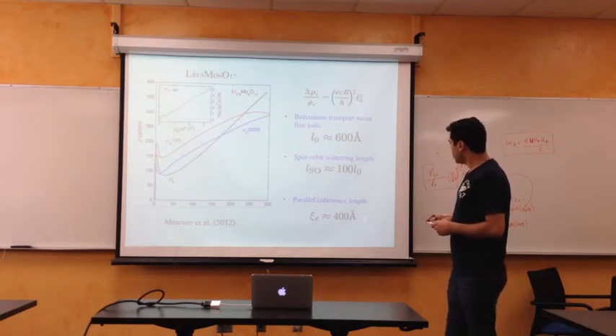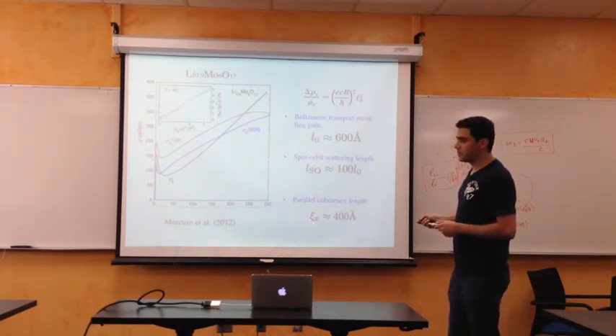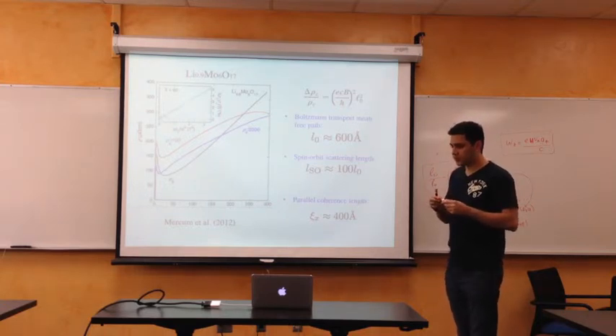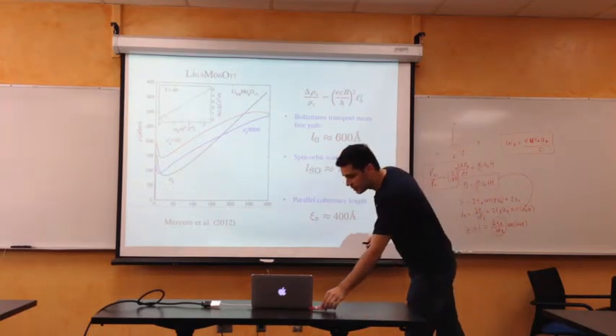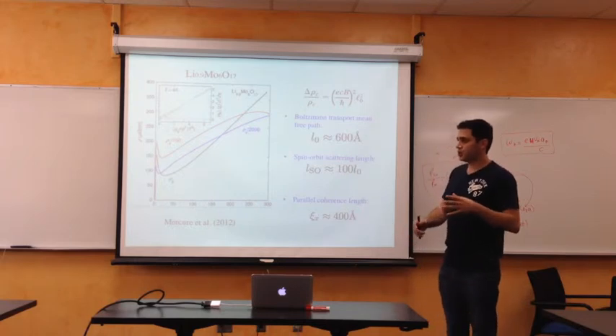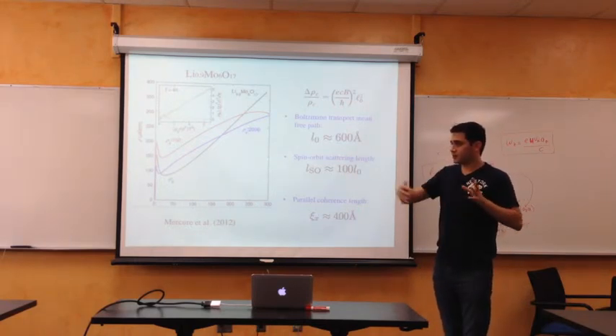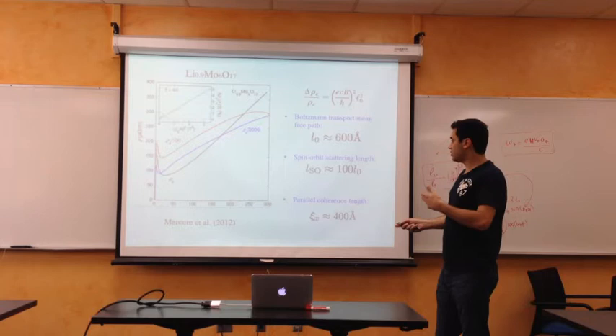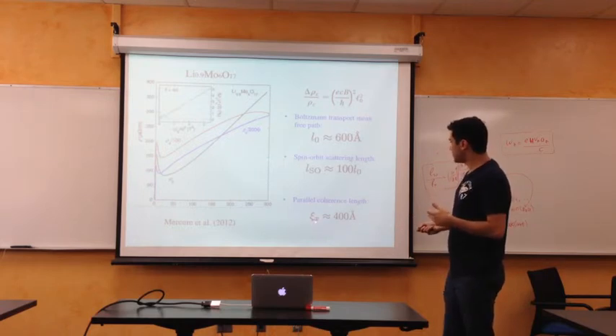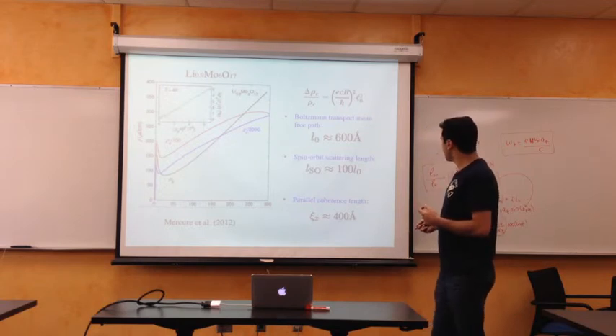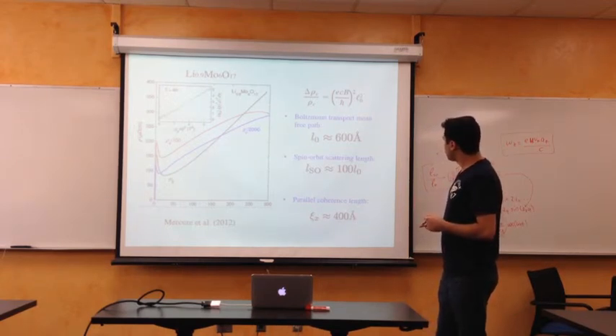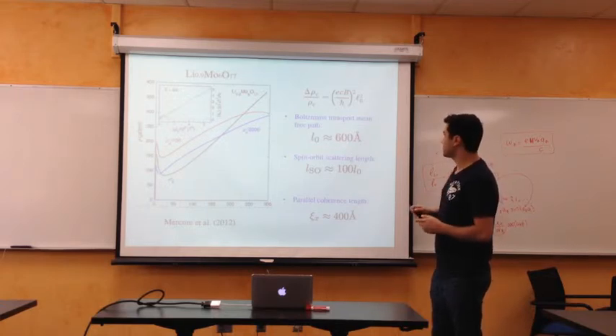Also an important number here to look at is the parallel coherence length. Now, coherence length can roughly be thought of as a length scale on which superconductivity varies spatially - you can also think of it as the typical size of a Cooper pair. So again, this number turns out to be comparable but smaller than the Boltzmann mean free path here.